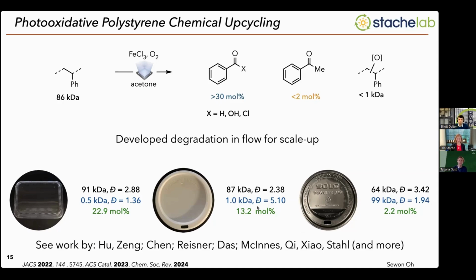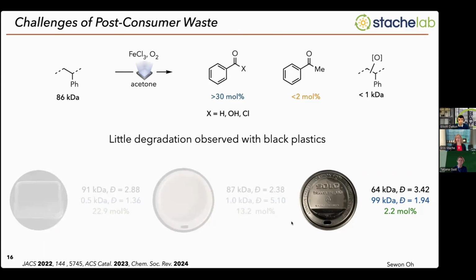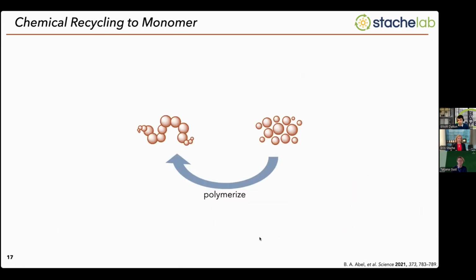But today I want to focus my talk really on our photothermal conversion work and depolymerization, which really was inspired by the fact that this black coffee cup lid did not work in the photooxidative degradation. So we didn't really observe any degradation, and we hypothesized this was because the black pigment was absorbing all of the photons, dissipating that energy as heat, and then not enabling any chlorine radical generation. And so this drove us to think about chemical recycling to monomer.